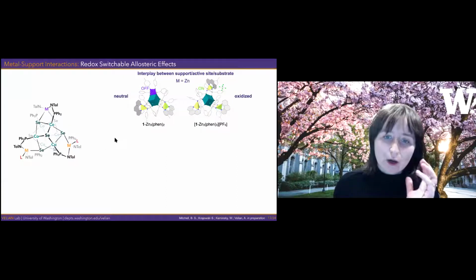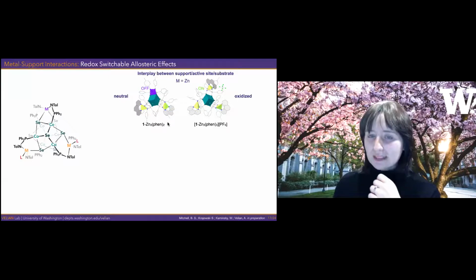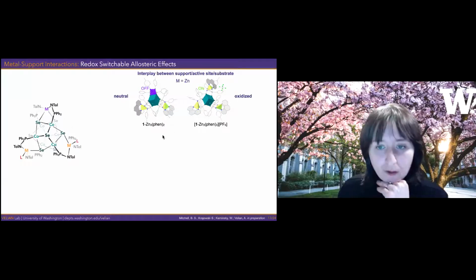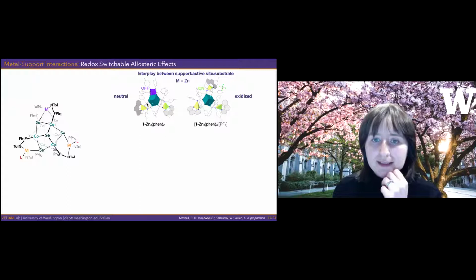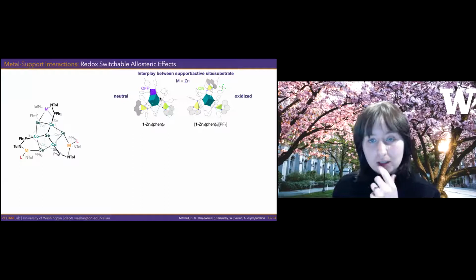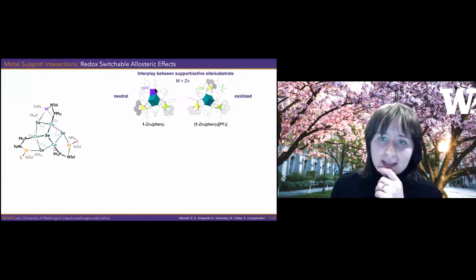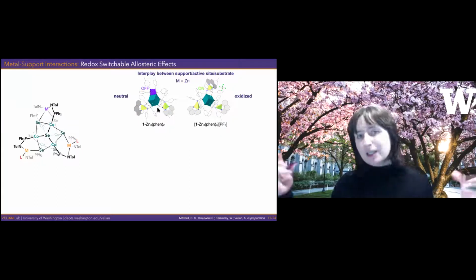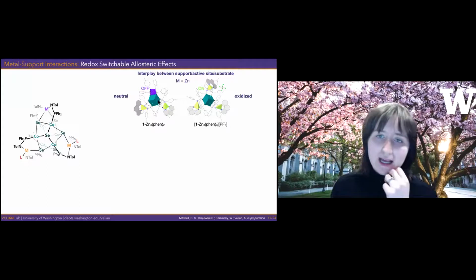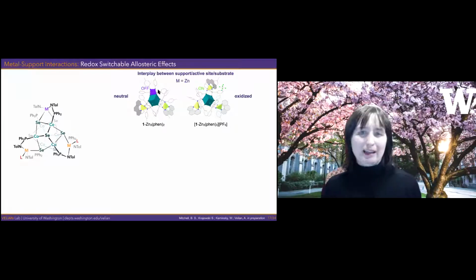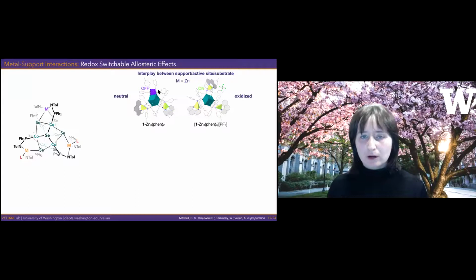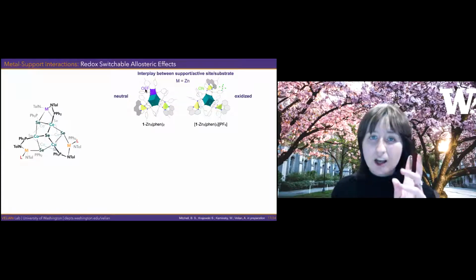And so if we now go all the way to zinc, what we see is that in the neutral form, here's the zinc cluster. I simplified the cluster core as this teal cube. And the three edge sites are pulled out of coordinating to the cube by phenanthroline. Two of the zinc sites are completely pulled out, not interacting with the seleniums. And then the third one is really coordinating to seleniums in this kappa 4 coordination mode. And I depict this as an off state.